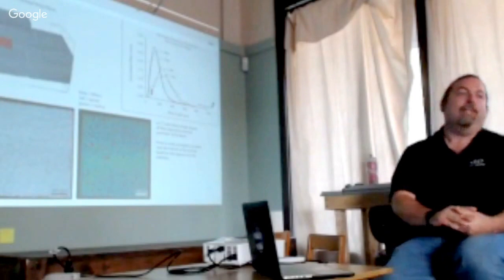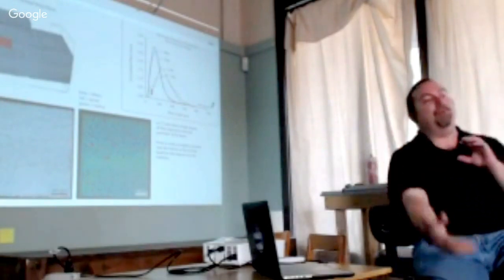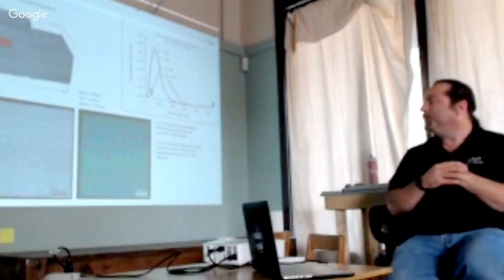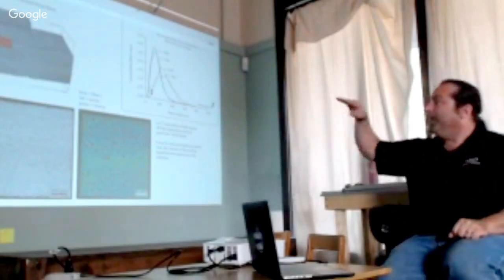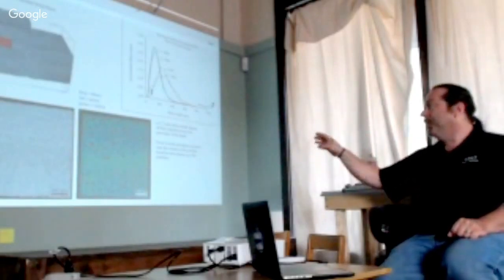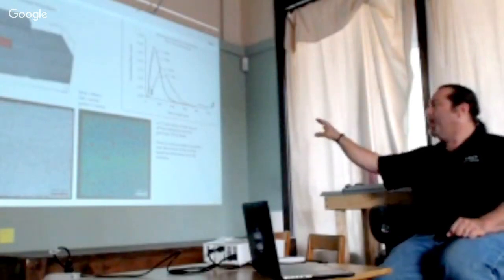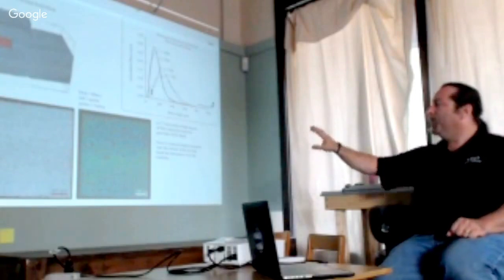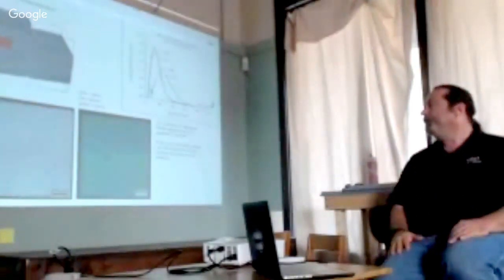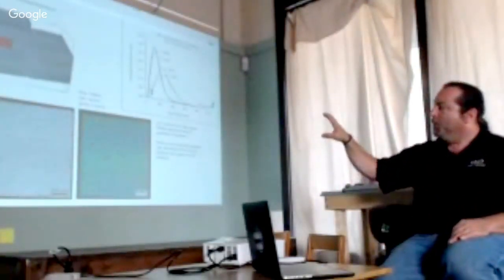And then there's a new type of micro CT scan. So this is like a computer tomography, but on a very high resolution, up to micron resolution. And then we could see in various slices through the material, both the porosity, and this slice is taken like right between the layers, and it's showing in red the porosity there. So there's a lot of voids in between the layers that really contributes to that low interlaminar strength. And then also we get the more details of the fiber alignment.